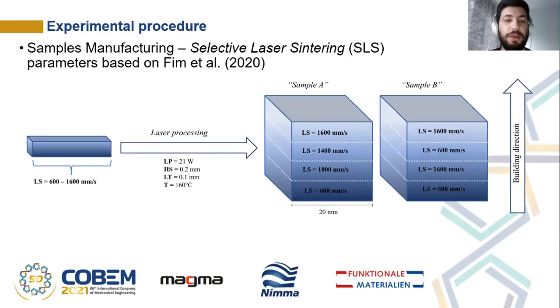At every 5 millimeter section, the laser scan speed value was varied, starting at 600 millimeters per second up to 1600 millimeters per second, promoting a gradual variation in the laser scan speed values. The second one, called the B sample design, consisted of printing alternate 5 millimeter height sections using only the extreme laser scan values. For comparison purposes, reference samples were obtained employing each laser scan speed value, varying the height between 20 and 5 millimeters, called samples C and D, respectively.